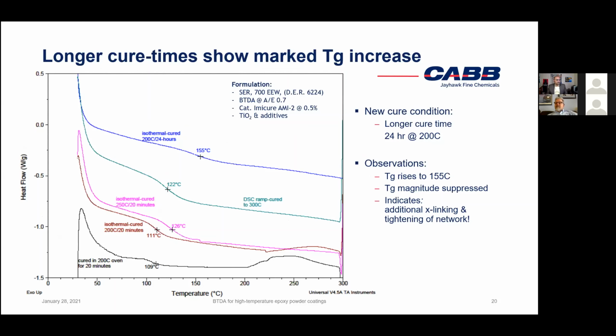That's a very good question. And actually, we did look at the residual cure exotherms. And as you can see, the bottom curve, the black one here, there's a significant residual exotherm. And so we were monitoring those things. What happened was after a little bit of changes, we started not being able to get that residual exotherm. Look at this pink curve, there's nothing here. And the green one, there's nothing here. So we couldn't detect how much more exotherm could have come out. And this is frankly what really surprised us, that this curve looks like there is nothing left to cure, and yet when we allowed the curing to occur more, it bumped up the TG and suppressed the TG too.